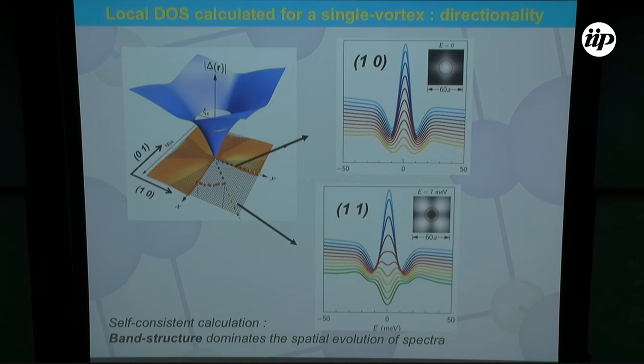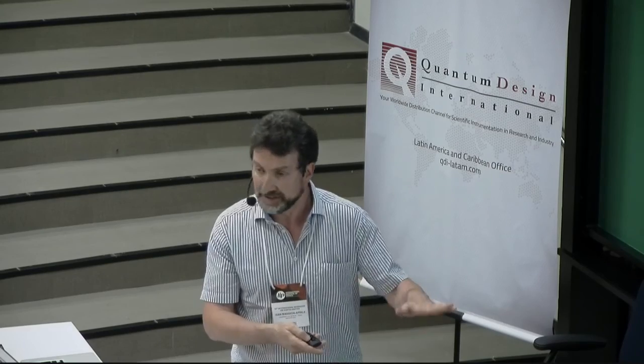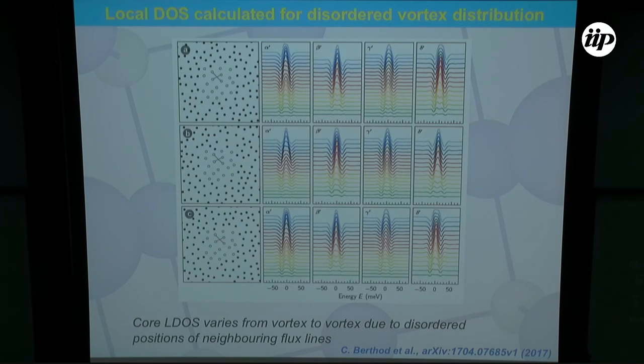If you would do the same analysis with an S-wave vortex, essentially you would find the same evolution. So it's really a question of band structure of the material, and this dominates the spatial evolution of the spectra. Another point concerns the surrounding vortices. So I told you that we were generating random distributions of vortices. Actually, there were 600 distributions which were generated.